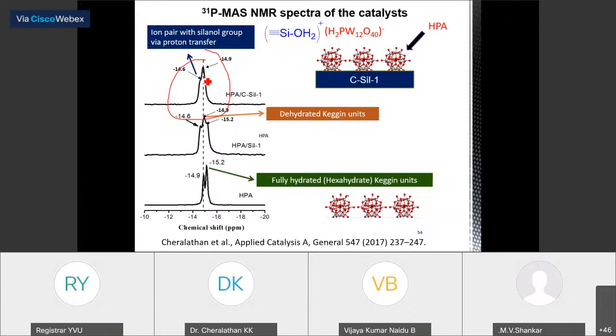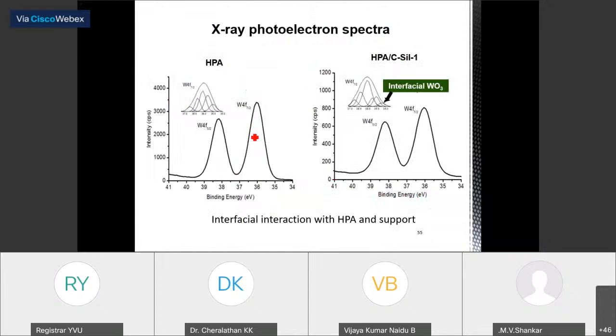That means all this HPA is bonded to the silica surface. It gives stability to this catalyst. That is why it is not leaching out. And we even confirmed this by using XPS analysis. We found interfacial WO3 present in this material which we have prepared. By this way, we confirm connectivity.